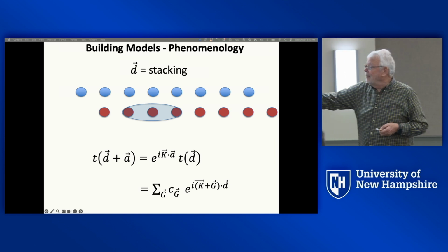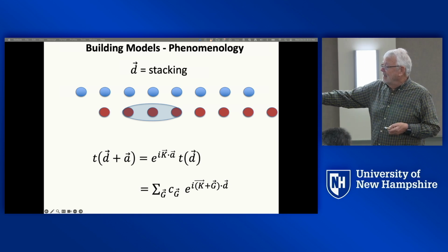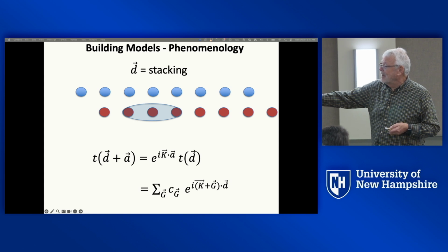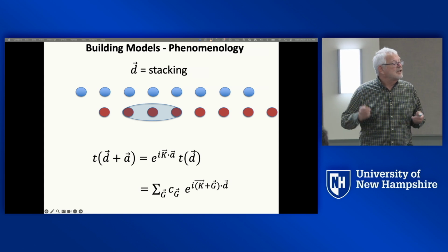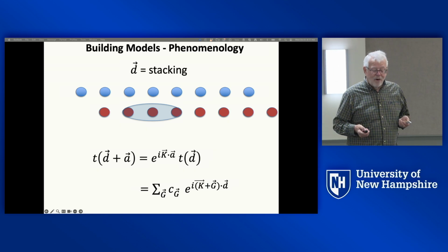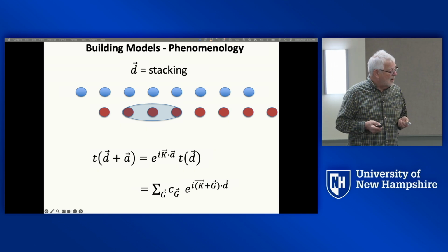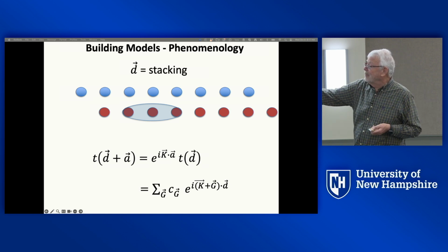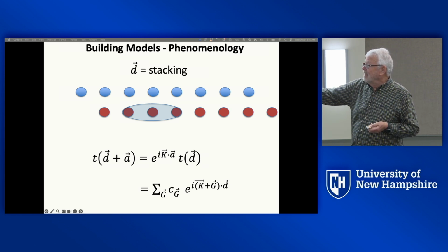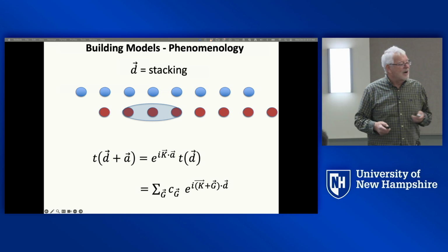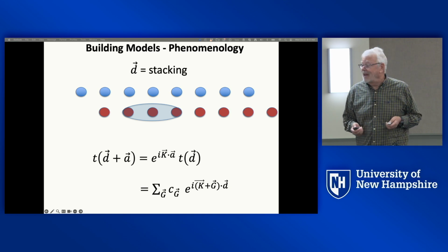But the range over which the dominant tunneling processes occur is atomic scale, maybe a few lattice constants, whereas the period of the Moiré is much, much longer than atomic scale. And that means that on the Moiré scale, this tunneling from layer to layer is practically a local function. You tunnel from one position in the Moiré pattern to the same position in the Moiré pattern.